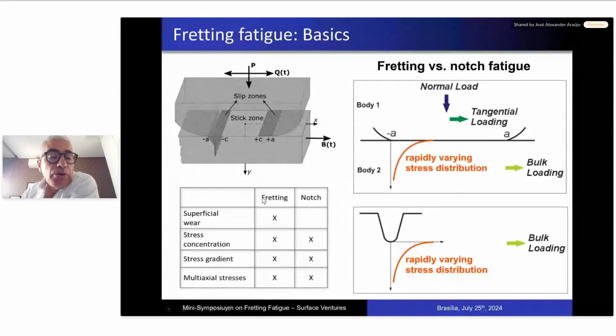In this table, we summarize this comparison, where you can see that in the fretting and in the notch fatigue problem, you have a number of similarities. You have stress concentration in both. You have stress gradient present in both problems. You have multiaxial stresses present in both problems. But in the notch fatigue problem, you do not have the presence of surface wear.